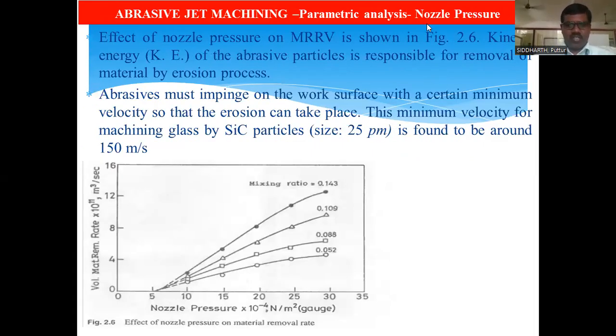And this is the effect of nozzle pressure. Here the effect of nozzle pressure on material removal rate in volume is shown in this figure. If the nozzle pressure is increasing, the material removal rate is also increasing. This means the kinetic energy of abrasive particles is responsible for the removal of material by the erosion process. Abrasives must impinge on the work surface with a certain minimum velocity so that erosion takes place. This minimum velocity for machining of glass by silicon carbide particles of 25 micrometers is found to be around 150 meters per second.